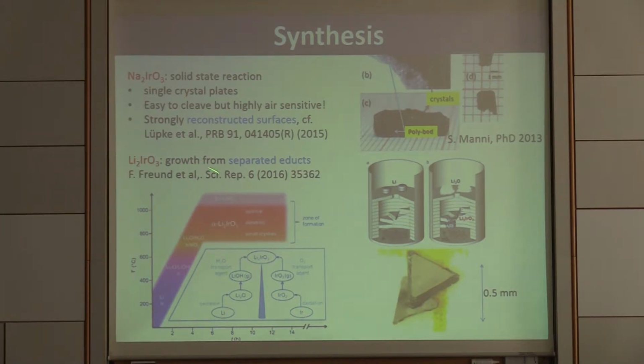Lithium iridate for a long time was only available as powder, and Anton Jesche and Friedrich Freund in my group actually invented a new method to get first crystals of that. The method sounds very weird because instead of properly mixing the educts for the oxidation process, which is typically done when you prepare oxide samples, here they work with an entirely different concept, which was found by accident, of course. We place iridium metal and lithium metal in a crucible, but we put them very far apart from each other, and then we heat up in an uncontrolled way, just in an open box furnace.